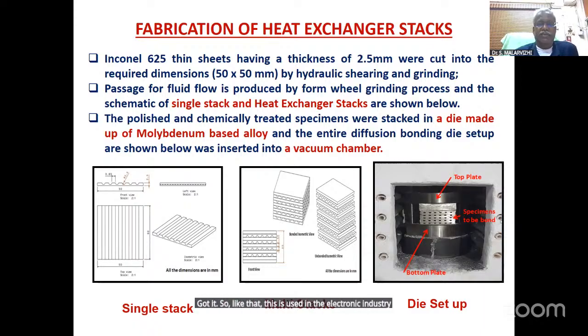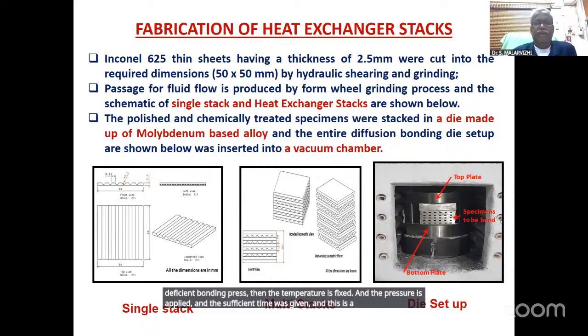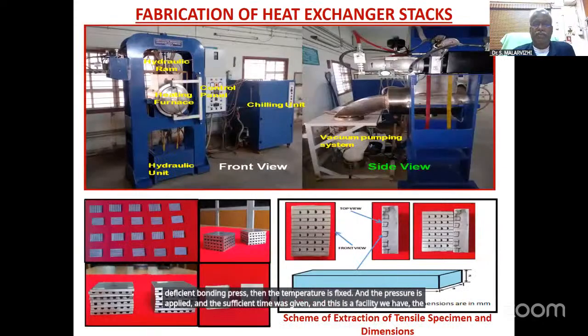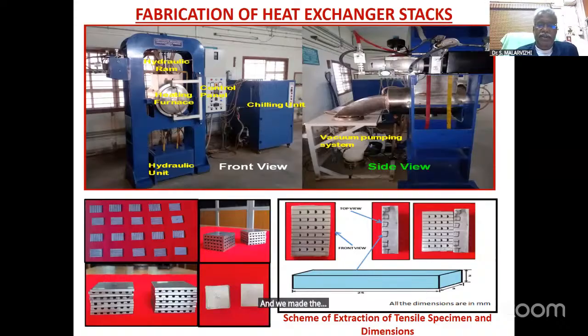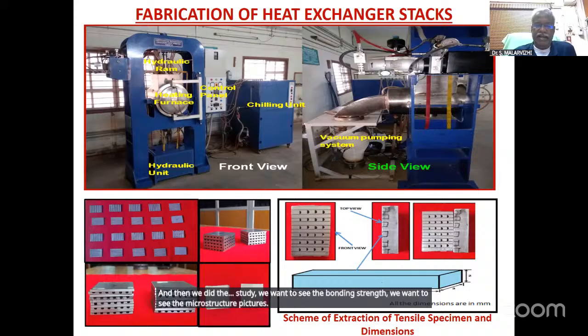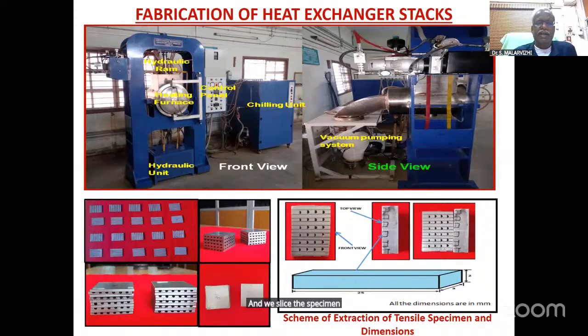So all these stacks, 10 sheets, are stacked in the vacuum furnace, the diffusion bonding press. Then the temperature is fixed and the pressure is applied and sufficient time was given. And this is the facility we have, the high temperature diffusion bonding facility in our center. And we made the heat exchanger stacks using this process. Then we did the study. We want to see the bonding strength. We want to see the microstructural features, and we sliced the specimen to study all these characteristics.